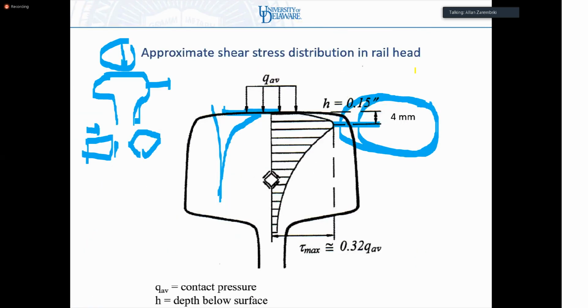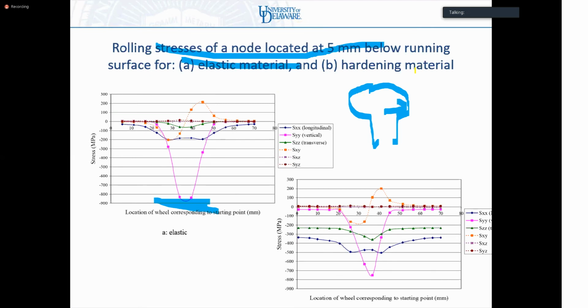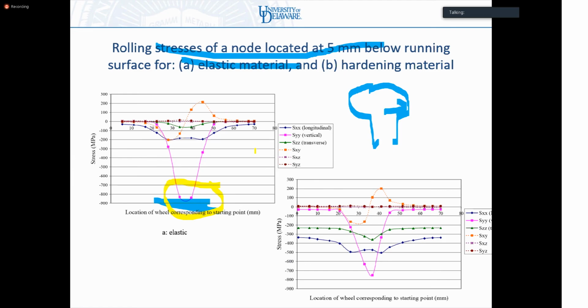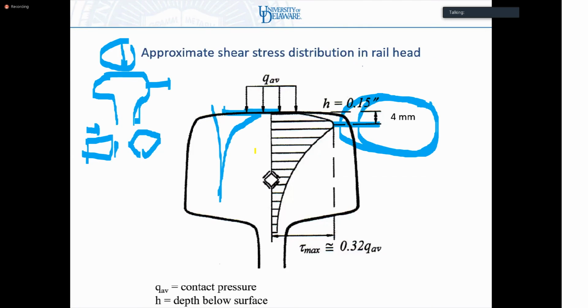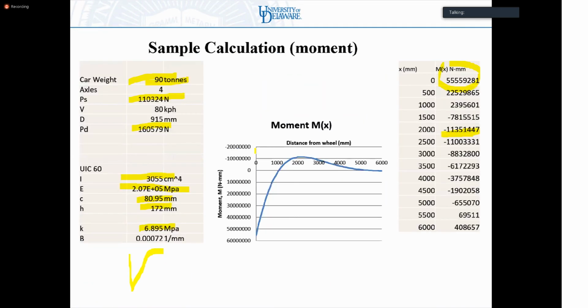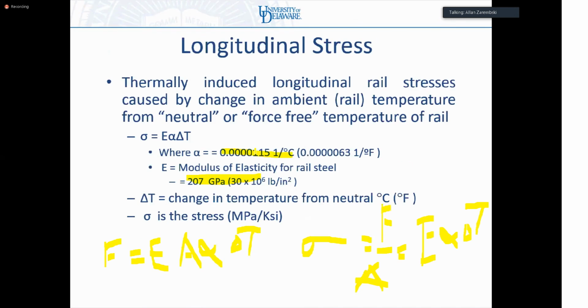Okay, so if we go back to our contact stress, my contact stresses are of the order of 900 megapascals here, vertically. And so 30% of that would be 0.3 times that, roughly 270, 300 megapascals. My stresses at the bottom of the sleeper are about a tenth of that, or less. So there's a very small contributor of it.